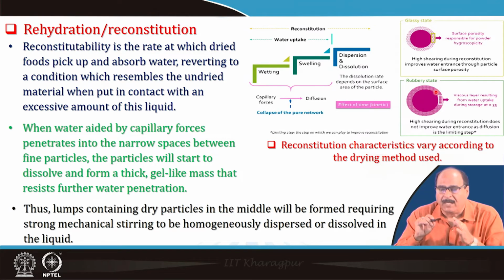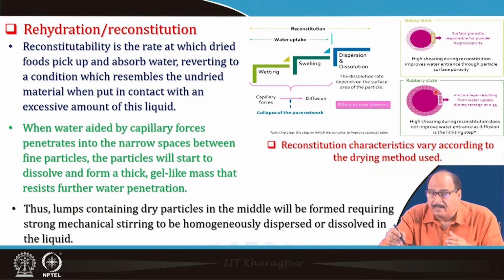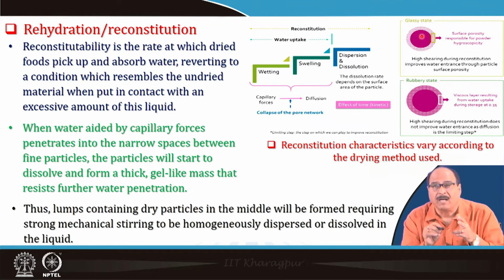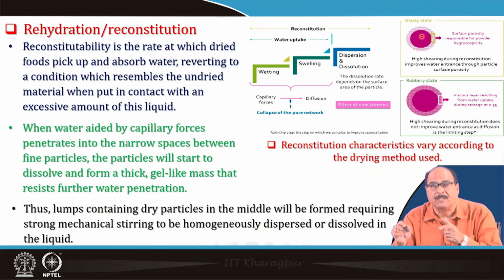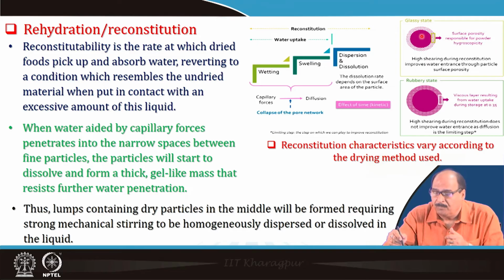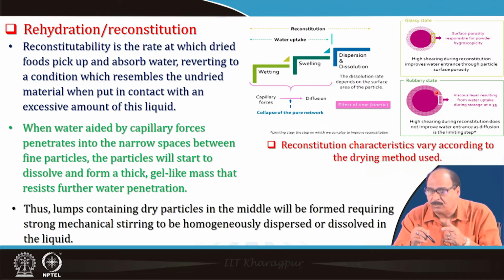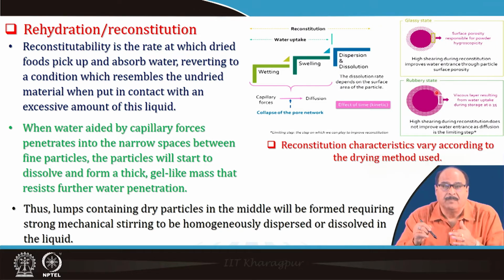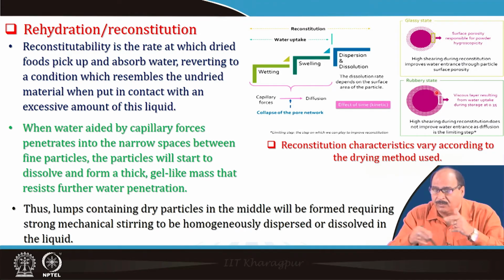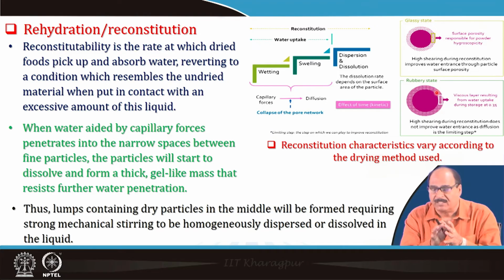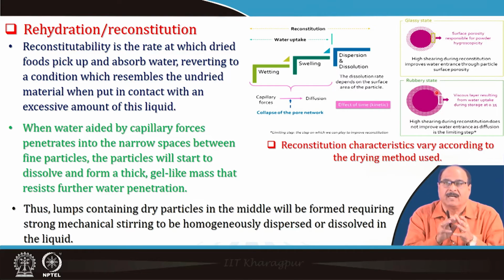Finally the dispersion is formed or the powder dissolves. The dissolution rate depends upon the surface area of the particle. Thus lumps containing dry particles in the middle will be formed, requiring strong mechanical stirring to be homogeneously dispersed or dissolved in the liquid. The particle will be in a glassy state or a rubbery state. In the glassy state, surface porosity is responsible for the powder hygroscopicity. So, high shearing during reconstitution improves water entrance through particle surface porosity, whereas in the rubbery state, where viscous layers result from the water uptake during storage at this water activity, high shearing during reconstitution does not improve it, because diffusion is the limiting step.